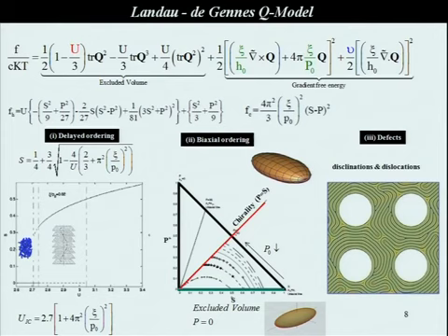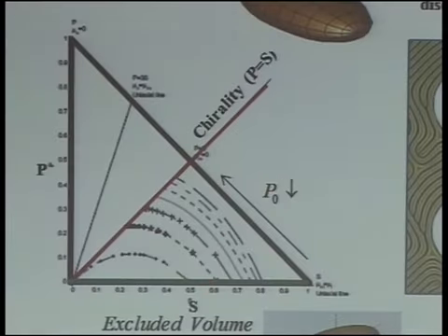So when P is equal to 0, as in a nematic, the pitch is infinity, so this term plays no role. So I'm minimizing the states, and the nematic states live on this line, P equal to 0. All these curves denote what happens when I change P0 from infinity, which is nematic, to 0, a fully biaxial line.